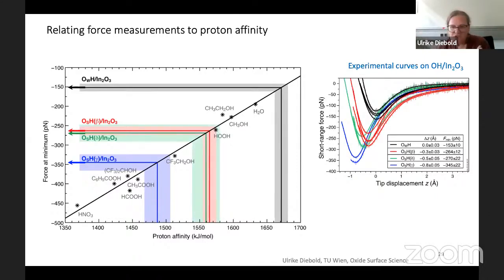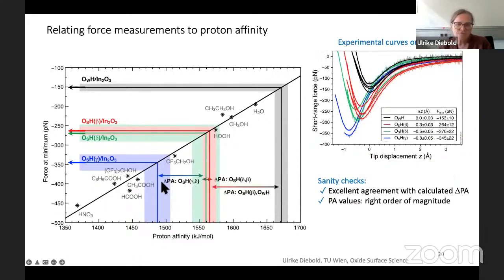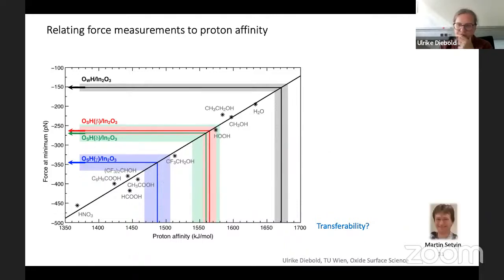So is this reasonable at all? It turns out that it's difficult to model absolute proton affinities, but changes one can model, and the changes agree really well. And also the PA values that we are getting are really in the right order of magnitude of what one needs to expect. So we've really found a way to, we think, determine or relate to these surface hydroxyls, 4 of them, 5 of them, the proton affinities. So that's very nice. The question is, how transferable is it? So we then tried to do this on another material.